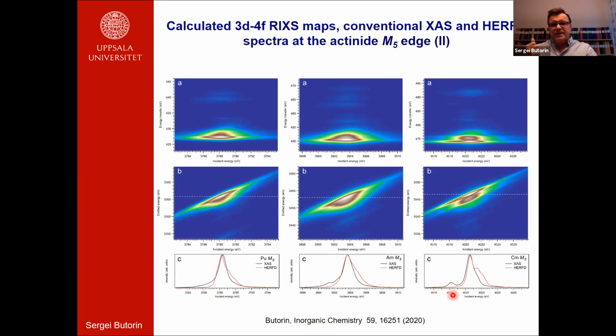But these differences, especially the lack of intensity on the low energy side, can be understood in terms of considerations which were described initially by Thole and van der Laan for L edges of 3d systems. So in our case, the high spin states of the 3d9 5f(n+1) multiplet will tend to group on the low energy side here, while the low spin states will tend to group on the high energy side here.